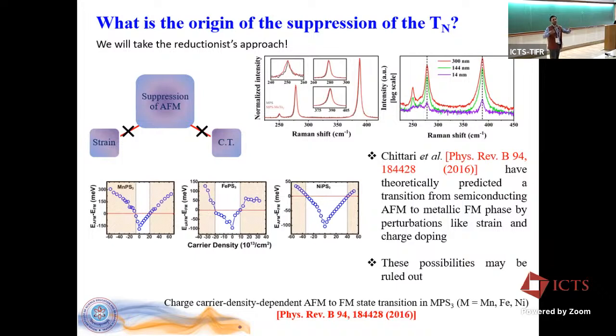So there was something we also had in mind, whether some other changes happen because of charge transfer. But such a degree of charge transfer is not possible without any bias or any other external mechanism. So we just did a plain experiment without any bias. And being an insulating, or semiconducting, system, such a huge charge transfer was not feasible. So we rule that out.